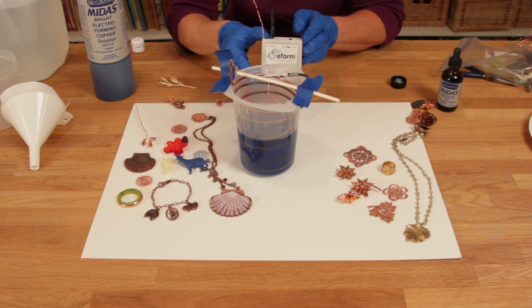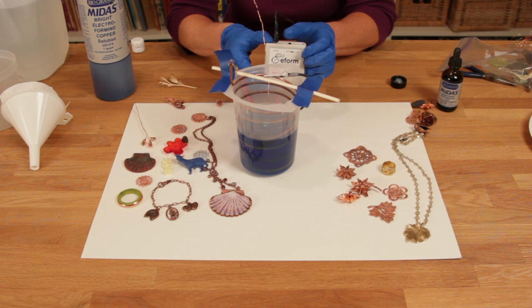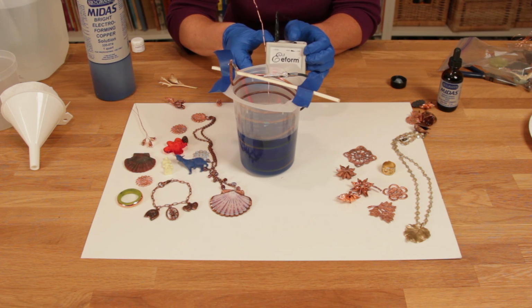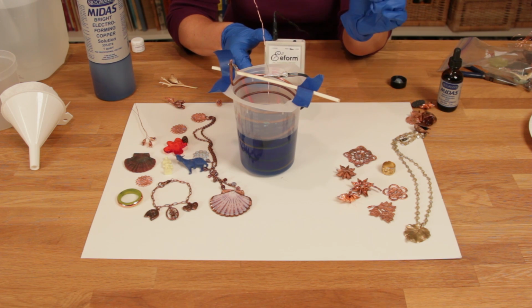Now on this piece, what I want to start at is a higher setting for maybe 10 minutes to get a nice coating on there, and then I'm going to back it off to a lower setting. The piece I have in there has a lot of sharp protrusions, and the lower setting will keep it from forming little copper spikes around the edges.